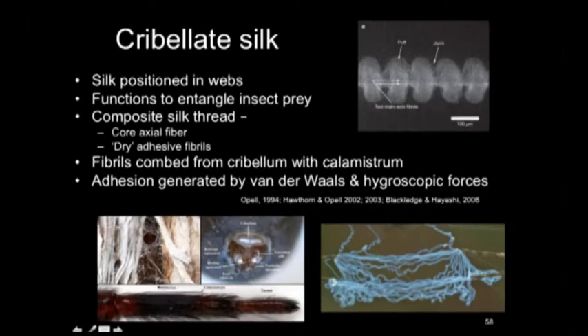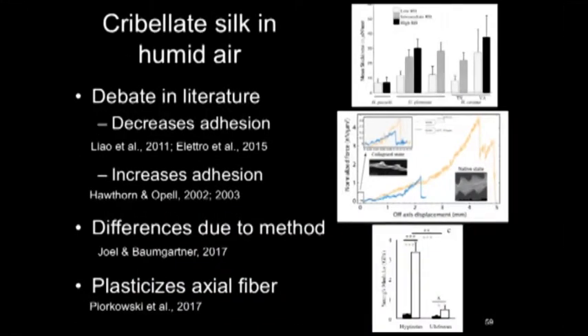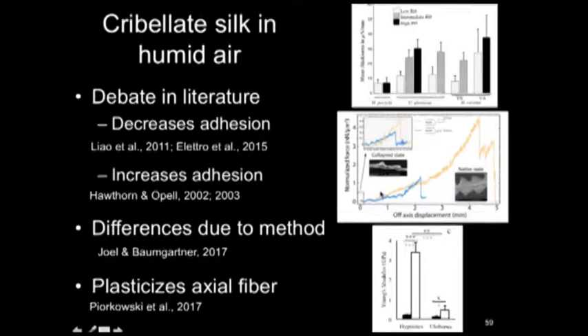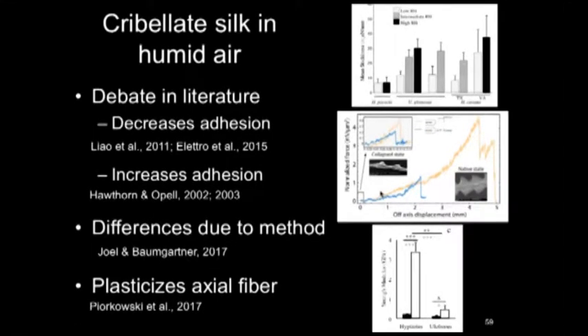However, there is a bit of debate as to the effects of water. In some cases, several studies have showed that there's a decrease in adhesion where the fibrils collapse, so that at dry conditions they seem to function rather well, but when they're exposed to a fine mist, the water in the air causes them to bind together and collapse. However, other studies have shown that at higher humidities, they actually increase adhesion, and that adhesive force is increased.